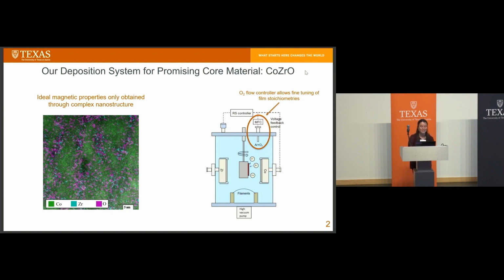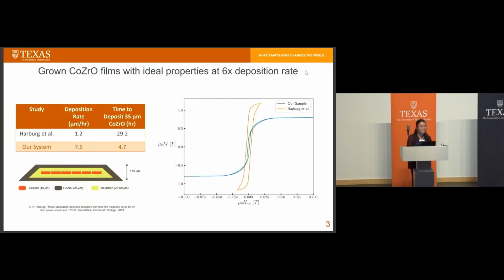So for our project, with our collaborators at the Southwest Research Institute, we've developed a DC reactive magnetron sputtering system for cobalt zirconium oxide. And I wanted to highlight that it includes a controller for the oxygen flow into the main sputtering chamber, which allows us to precisely fine-tune the film stoichiometries and also reduce the level of poisoning on the targets themselves, which helps us actually achieve incredibly high deposition rates. So finally, I wanted to show some of our results so far. We've gone through several rounds of iteration.